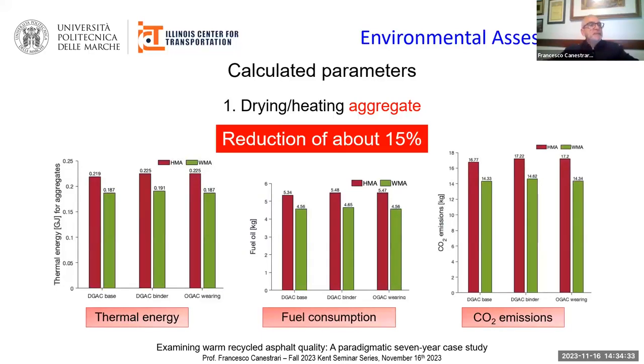Then the calculated parameters during the dry heating phase of the aggregates, in terms of thermal energy, fuel consumption, and carbon dioxide emissions, exhibit a reduction of about 15%. And these results are perfectly in agreement with the real data of the fuel consumption collected at the asphalt plant.